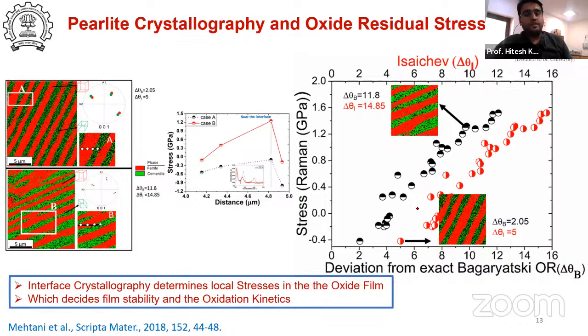All these experiments were done on a coarse pearlite structure. Because of the limitation of our characterization technique, we can't do these experiments on the fine pearlite structure. So we can say, from these indirect measurements, that when we align the pearlite colonies, the interface becomes less deviated from the Isaichev and Bagaryatsky orientation relationship, and that interface enhances the oxidation resistance and corrosion resistance of the material.